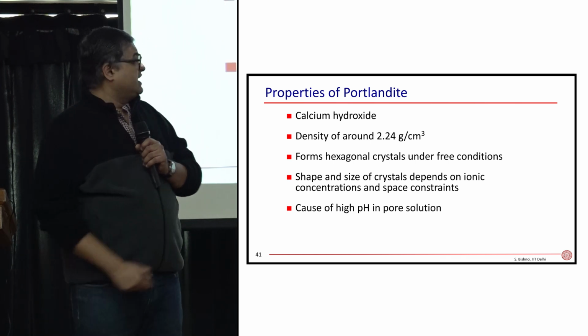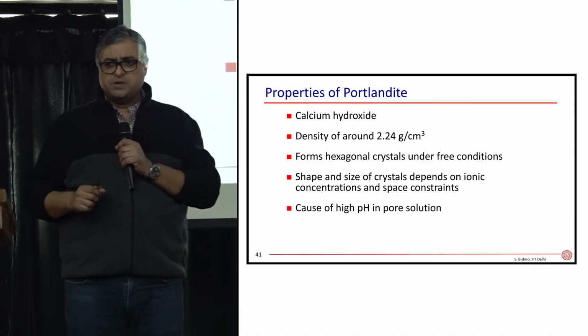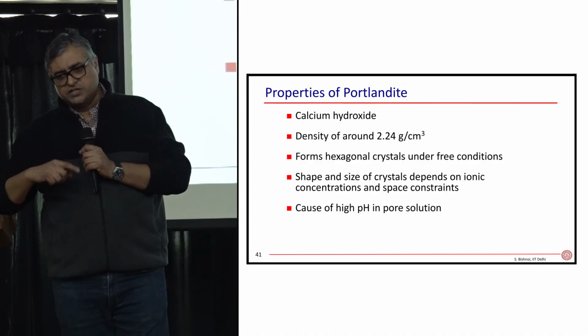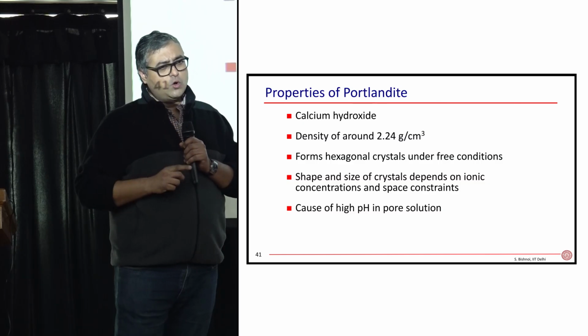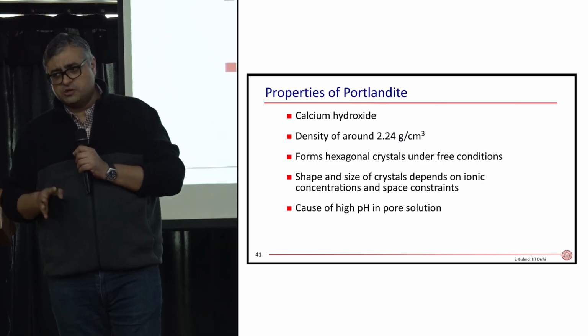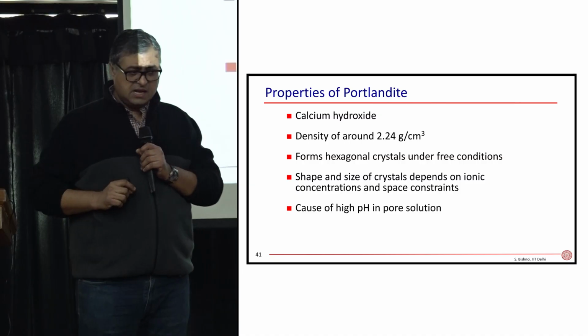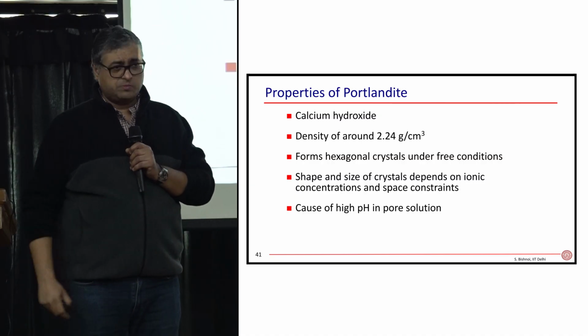hydration of silicates is calcium hydroxide. Because you remember, silicates were C3S or C2S. For every silicon, you only need like 1.2 to 2 calcium to produce a calcium silicate hydrate. So the remaining calcium goes to produce calcium hydroxide.